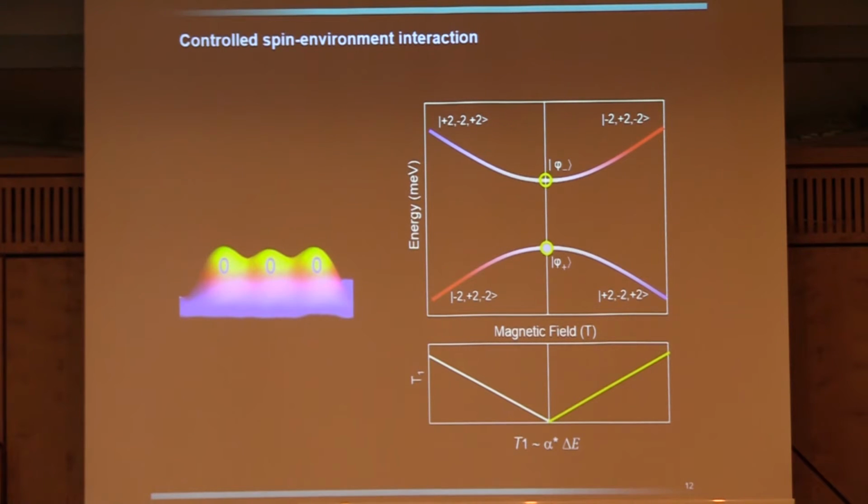Both are non-magnetic. If you calculate the transition intensity between them, you find that the spin relaxation time of this is extremely short. But if we now apply a bias field by our external magnet, we move out of this avoided level crossing. The ground state becomes more the Néel state, where the two spins are aligned with the magnetic field, and the excited state is then the opposite. And it turns out the spin lifetime evolves linearly as a function of this perturbation.